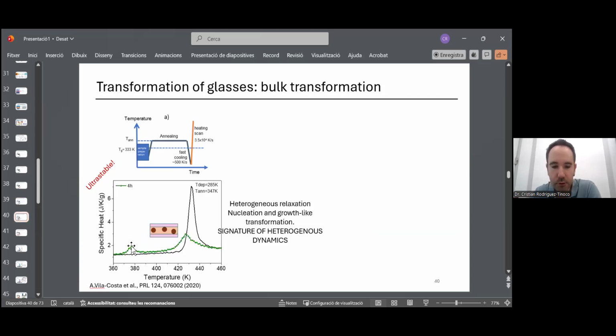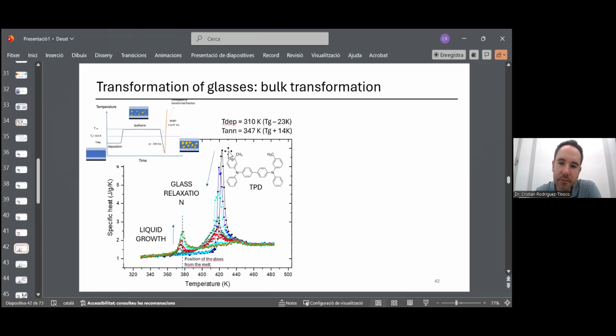And this process continues until eventually the whole system is a fast cool glass. Okay, so everything has become a liquid at this temperature. Okay, so this is the full process. Okay, we see this relaxation of the glass, which we call softening, and we have this emergence of the fast cool glass, which is related to the emergence of this liquid phase in the glass. Okay.